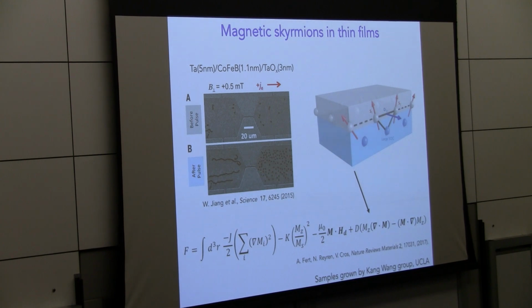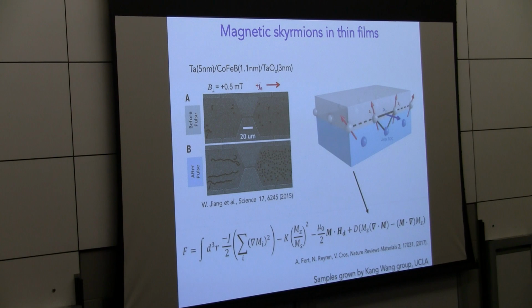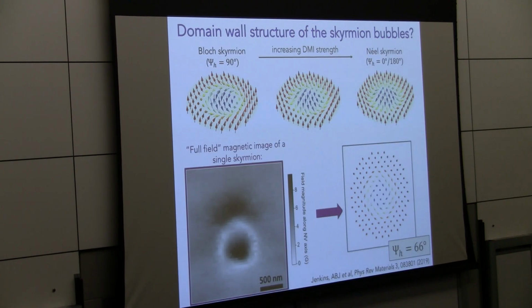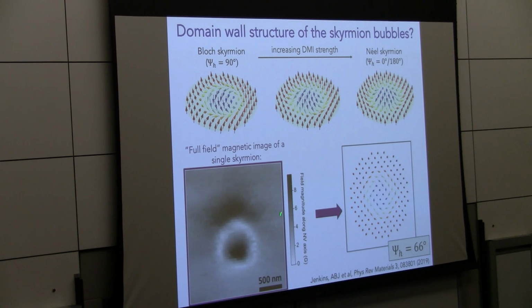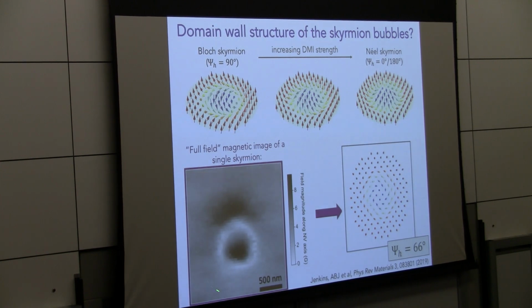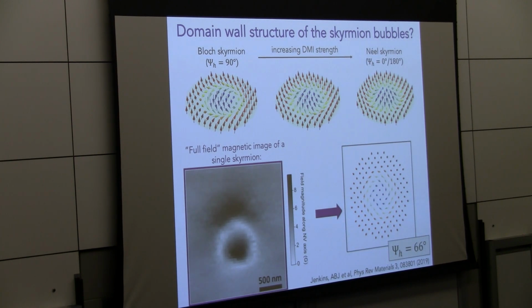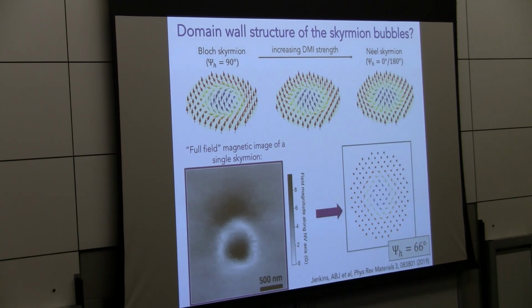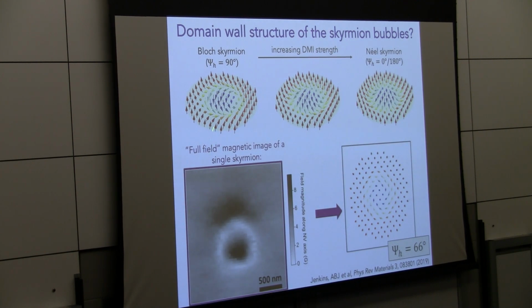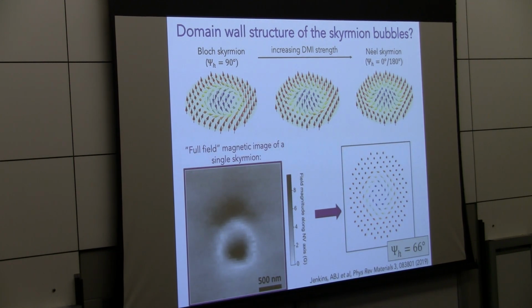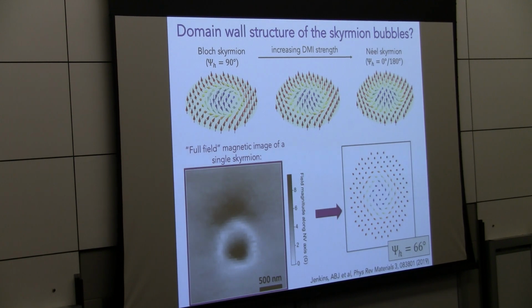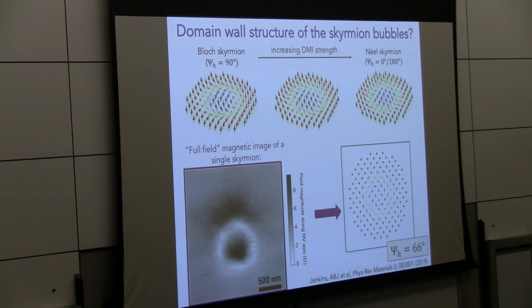And you can see that their spatial resolution is, of course, limited by the optical diffraction limit of their MOKE. And so we worked with them to image the internal spin structure with higher spatial resolution. Here is one NV image that we've taken of a single skyrmion in these devices. One of the questions we wanted to ask is, what is this internal spin structure of the skyrmion? There's a continuous range of types of skyrmions, but one can think of, when you remember domain walls, you can have Bloch type domain walls or Néel type domain walls, where at the domain wall, do the spins point azimuthally, or do the spins point radially as you cross the domain? So the spins, do they flip like this, or do they flip like this?